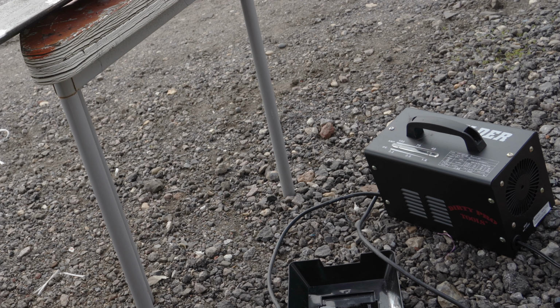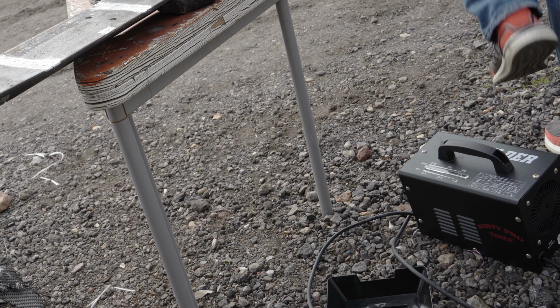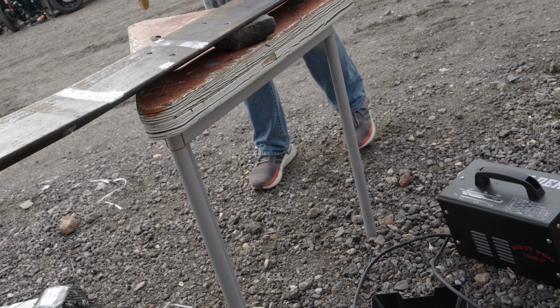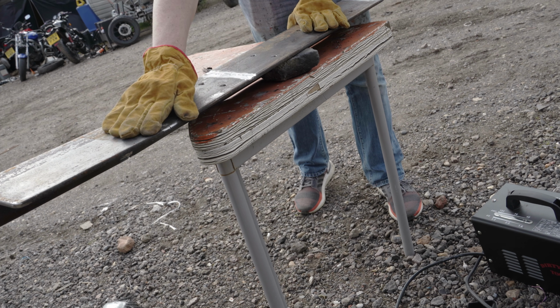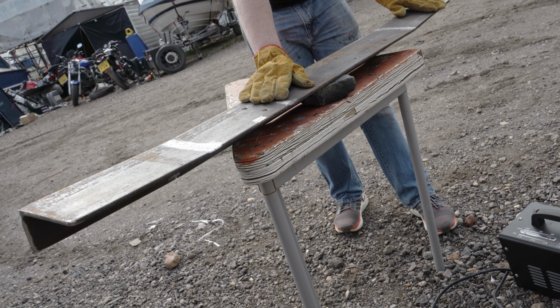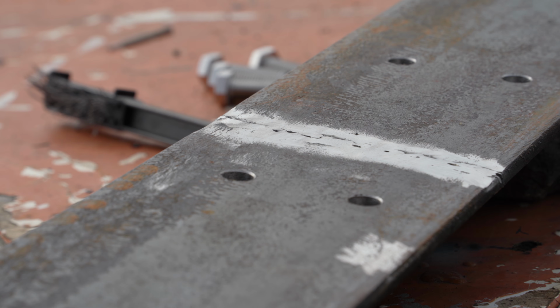The steel was 8mm thick, and I do fear that my 100 amp welder is a little puny and might have been jointly the culprit for my electrode getting stuck, alongside my rookie technique. But the steel is now all back together, albeit with a handful of little gaps I couldn't fill for the life of me. Epoxy paste will come to the rescue.